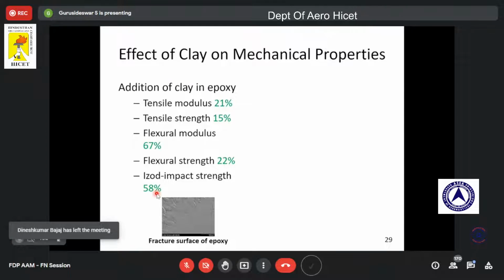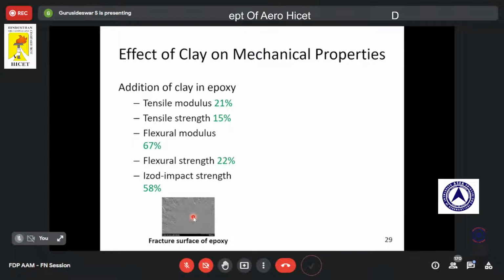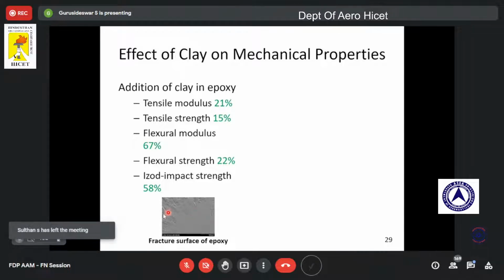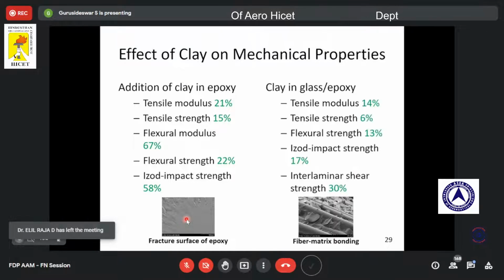So this is a typical fracture surface of an epoxy. This is the figure taken after the tensile failure. We took the failed sample to the scanning electron microscope, and then we took this micrograph. This shows a typical brittle failure, as we can observe from this micrograph.